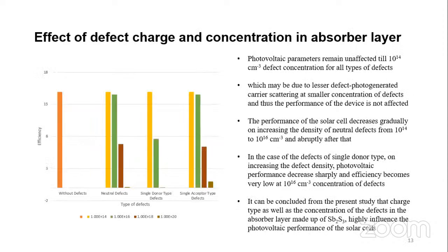We have studied the effect of defect charge as well as concentration in the absorber layer. We have varied the concentration of defects in the absorber layer, that is Sb2S3 material, and we have also varied their charge types. We have studied the changes in the photovoltaic parameters with charge types of the defects. We have observed that the photovoltaic parameters remain unaffected till a defect concentration of 10^14 per cubic centimeter for all types of defects. This may be due to lesser photogenerated carrier scattering at small concentrations, so we can see that the device performance is not compromised.